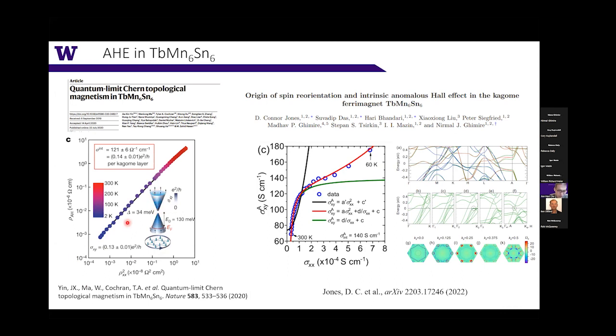And then they argue that this is due to this gapped spin-polarized Dirac fermion, according to work by Jiaxing and Hassan's group. Now, a later work by Nirmal and Igor found something different. They found that the anomalous Hall cannot fit very well by just the extrinsic and intrinsic contributions. That model corresponds to this black curve.